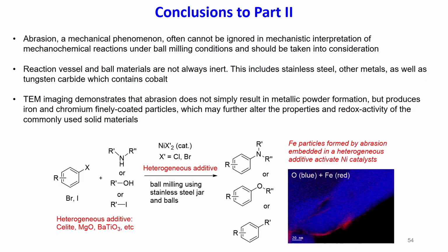So this is the main conclusion from this current work: in mechanochemistry, we cannot ignore mechanical phenomena like abrasion. Abrasion happens, and it always happens. Actually, even if you don't use any solid additives, it also happens, just to maybe less extent. But you must take it into account because that may affect the mechanistic interpretation.